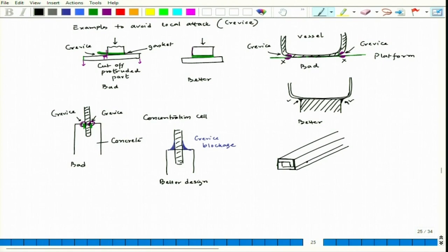Now, if we do spot welding here, these are the spot welding points. Whatever matching surface you create, there will be crevice segments here. So, this particular segment, there will be a small gap, and that gap can lead to crevice. Whenever we have such a situation, it is better to do continuous welding. If we do continuous welding like this over the entire segment, continuously we weld so that all those crevice gaps, all the small gaps can be closed down.